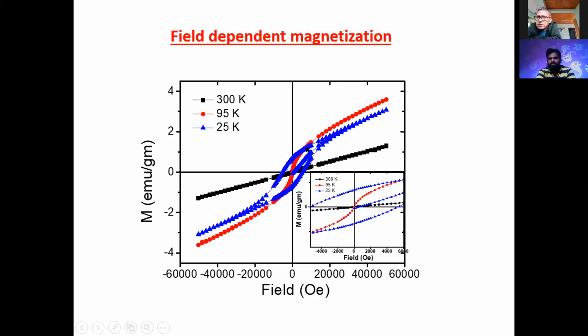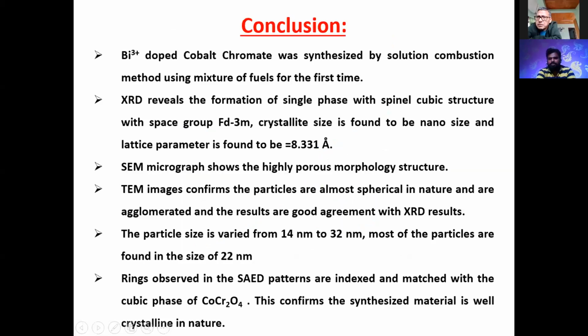Conclusion: this cobalt chromate was synthesized by the solution combustion method using a mixture of fuels such as urea and glucose for the first time. XRD pattern reveals the formation of a single phase with spinel cubic structure having space group Fd3m, and the crystallite size is found to be nano size and the lattice parameter is found to be 8.331 angstrom. SEM micrograph shows the highly porous nature. TEM images confirm the particles are almost spherical in nature with agglomeration, and the particle size results match very well with the XRD results.